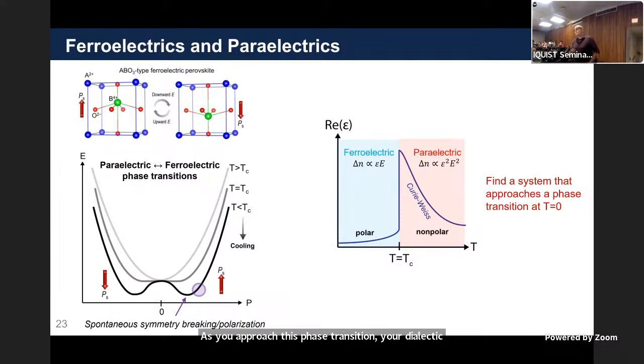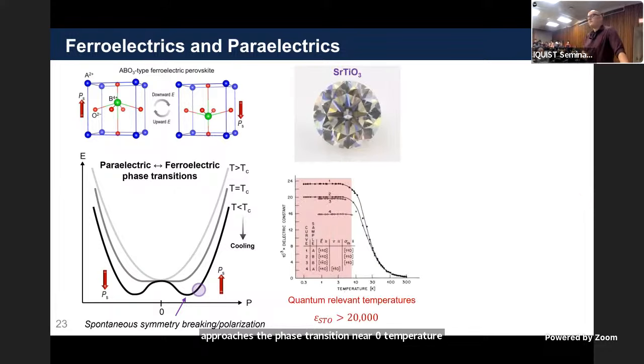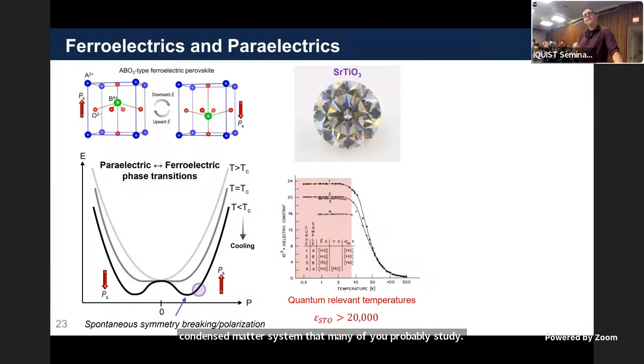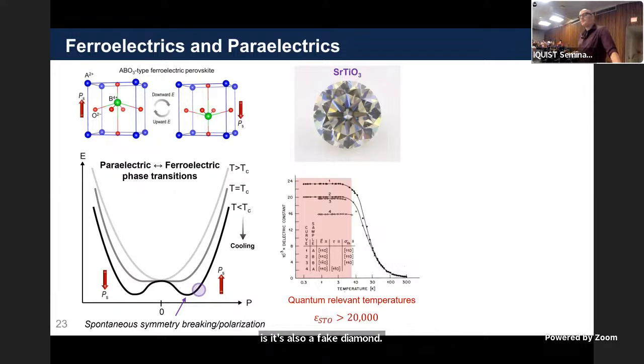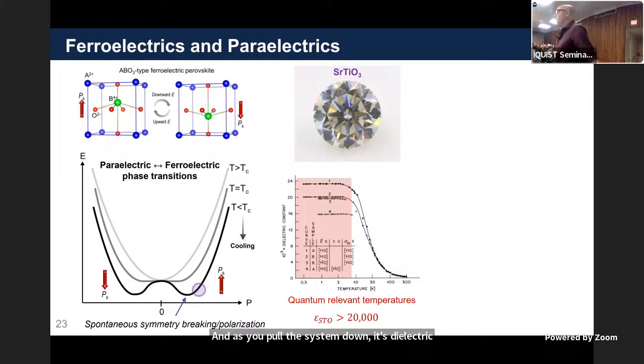And so if we simply want to find a system with a high dielectric constant to make a nonlinear optical system, we want to find a system that approaches a phase transition near zero temperature. And the exciting thing is that this type of system has been known for forever. It's the classic condensed matter system that many of you probably study, which is strontium titanate. And what I like about it is that it's also a fake diamond. It's a nice optical material that was used for fake diamonds for a while. As you cool the system down, its dielectric constant explodes to being greater than 20,000 at basically all quantum relevant temperatures, 10K and below. So strontium titanate is a great optical material that has crazy high dielectric constants at all low temperature ranges. And that's exactly what we were looking for.